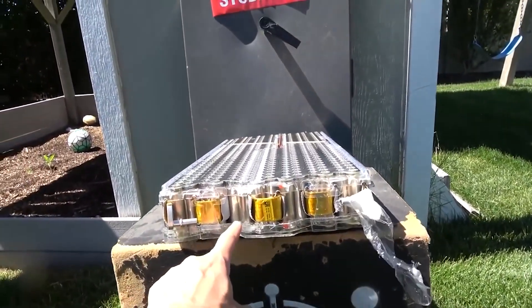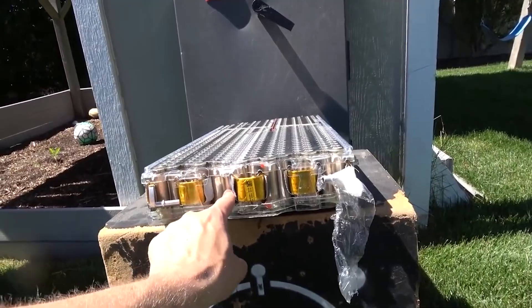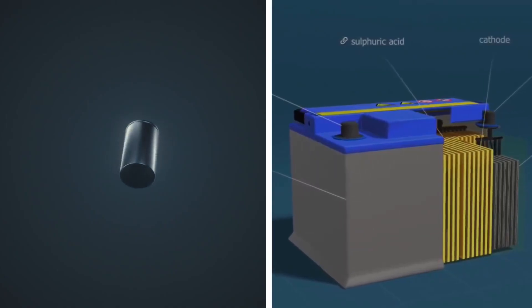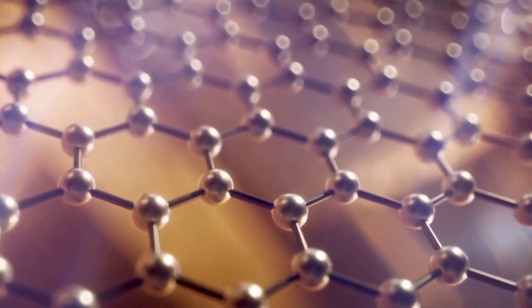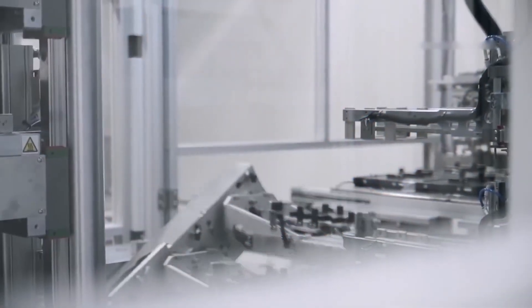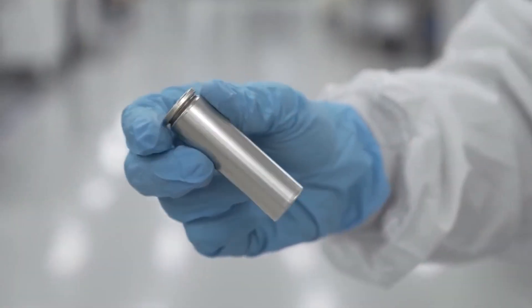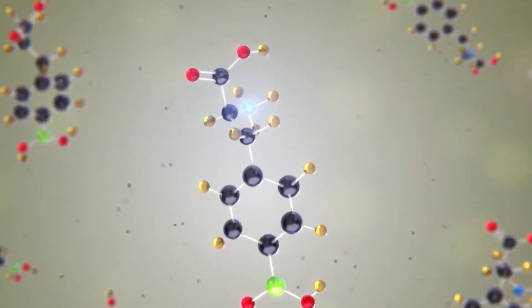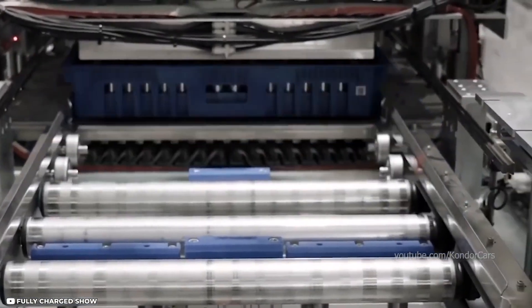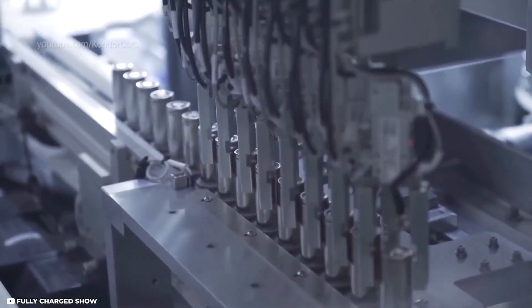The majority of commercial lithium-ion systems use a liquid electrolyte containing lithium salts such as LiPF6, LiBF4, or LiClO4 in an organic solvent. However, effective conductance is limited by the solid electrolyte interphase (SEI), caused by electrolyte decomposition at the negative electrode. Expensive membranes are required to separate the cathode and anode, as well as an impermeable casing to prevent leaking, limiting size and design freedom. Because they use flammable and corrosive liquids, liquid electrolytes pose safety and health concerns.